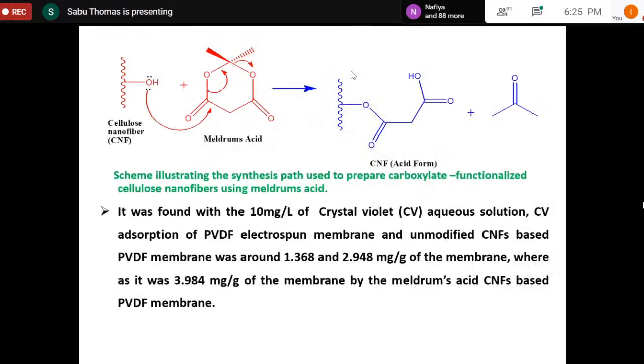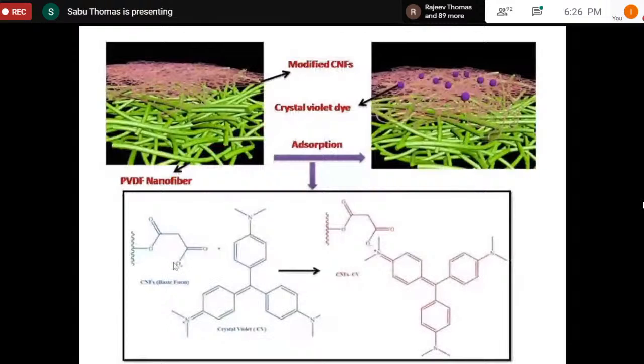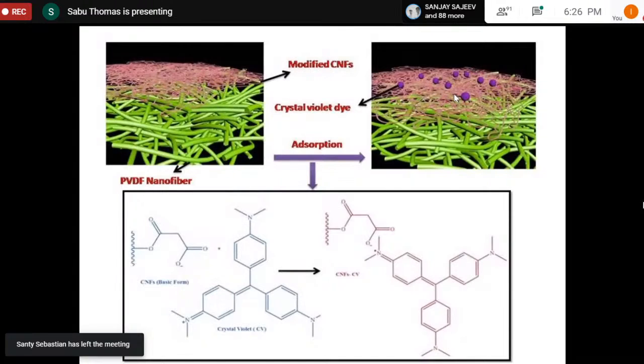You might be interested, you are all chemistry students, in what sort of chemistry we did. My PhD student did a very simple, green chemistry. This is the cellulose surface. Cellulose has beautiful hydroxyl groups. He made use of Meldrum's acid and did a very simple chemistry, and we introduced COO- groups on the surface of nanocellulose. So we made the nanocellulose surface electronegative. And you see what happened? This is the modified nanocellulose, and this is the crystal violet dye. Modified nanocellulose has a negative charge. Crystal violet dye has a positive charge. There is electrostatic interaction. That is why we could catch most of the dyes.